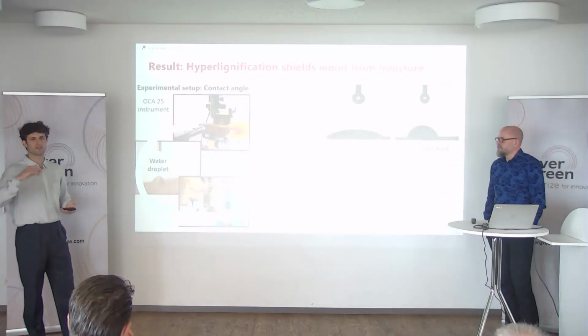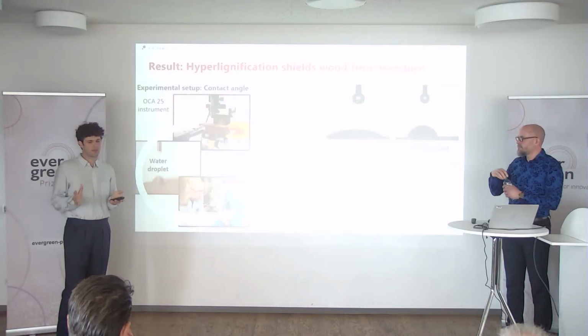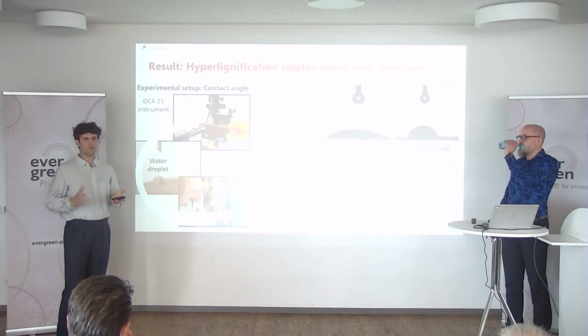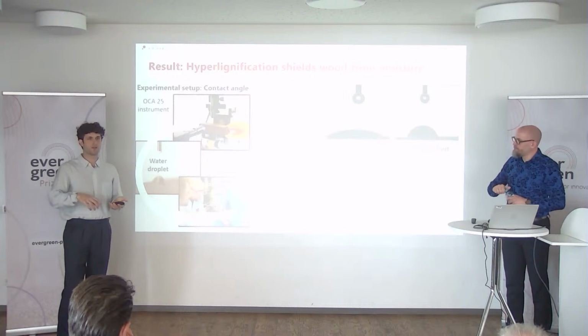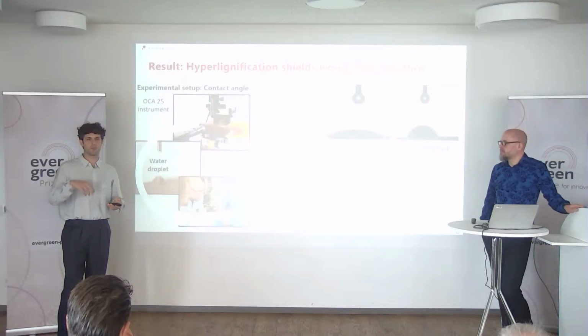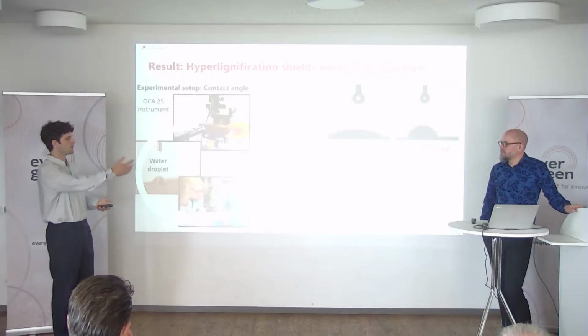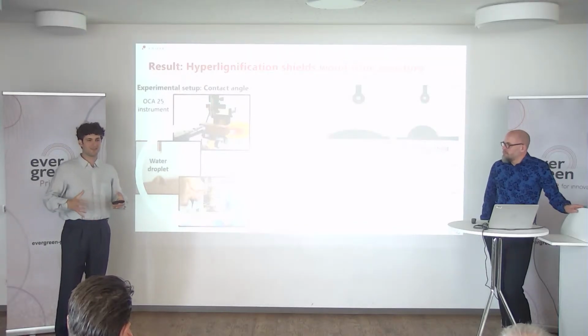Yes, we could see that when we're doing water contact angle, the water absorption is quite different because it looks like the lignin is blocking pores also in the other direction, not only in this region. It confines the absorption of water to the spot in which the droplet goes. And then, of course, in this case, it takes 2 minutes to absorb it, but we can see that it's more confined. It looks like the bulking also limits the spreading of the moisture within the structure.